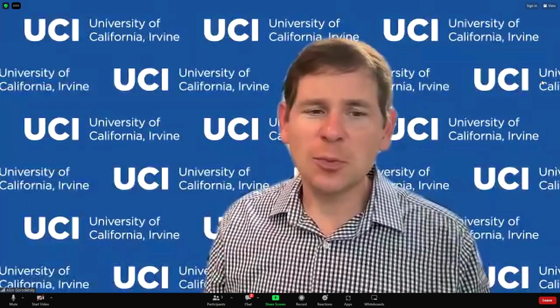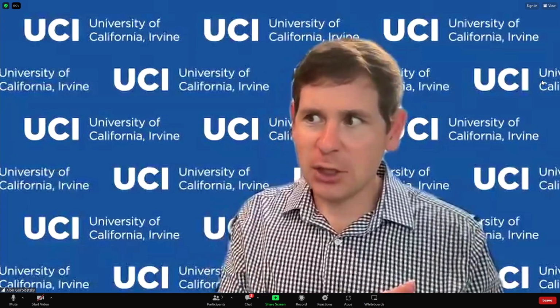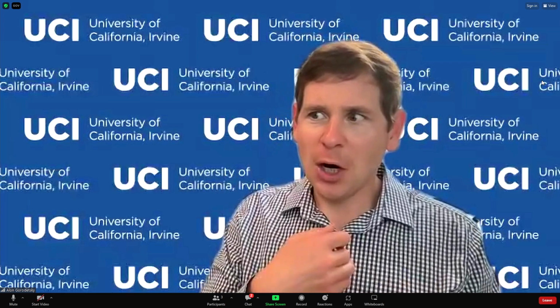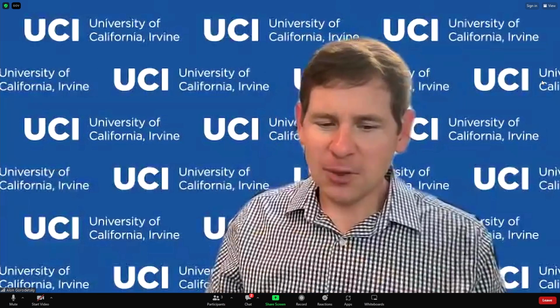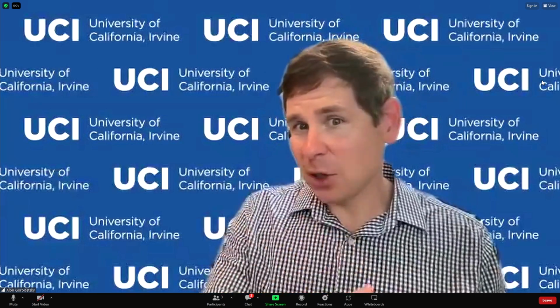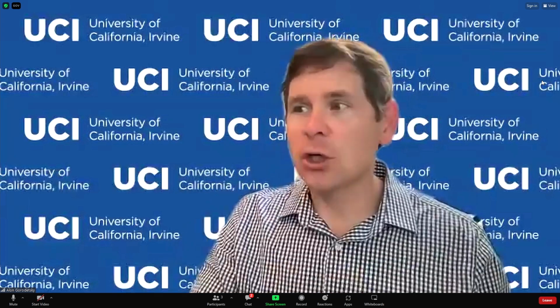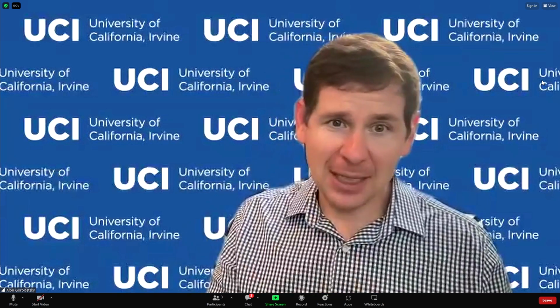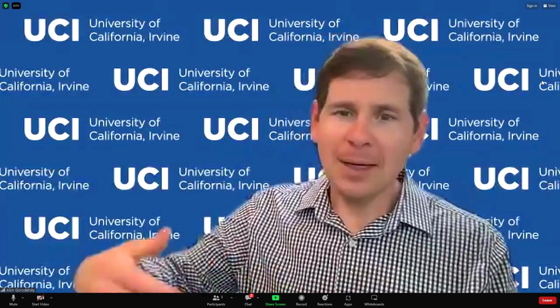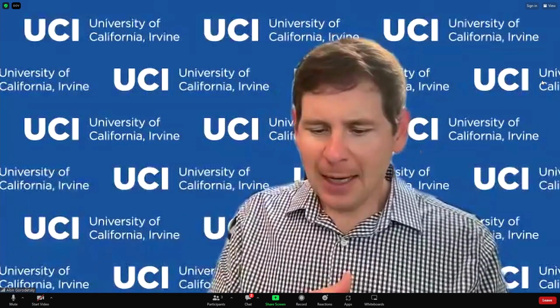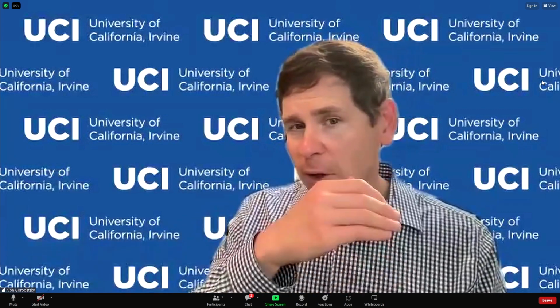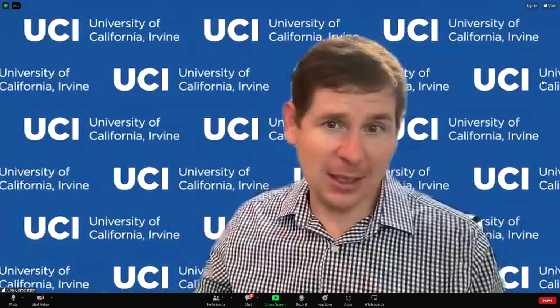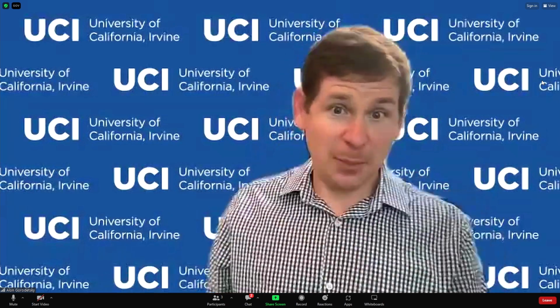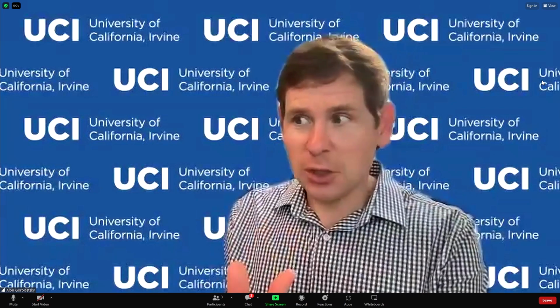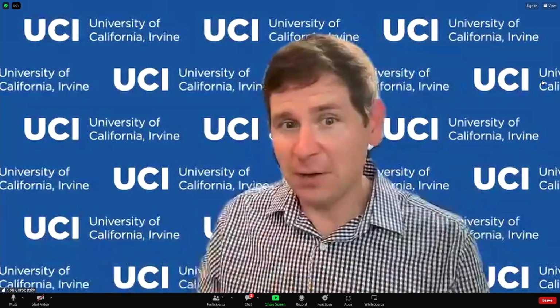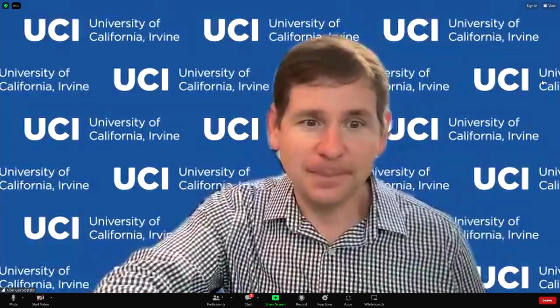So it's pretty consistent. I think it's just that our maximum values are at 100% strain, but the images where we're showing the change are only for 10, 30, 50% strain, and it's simply an experimental limitation, which one of my other students actually overcame recently. So that's just the difference. But those areal changes match exactly what you see at 30 and 50% strain. So that's a great question.